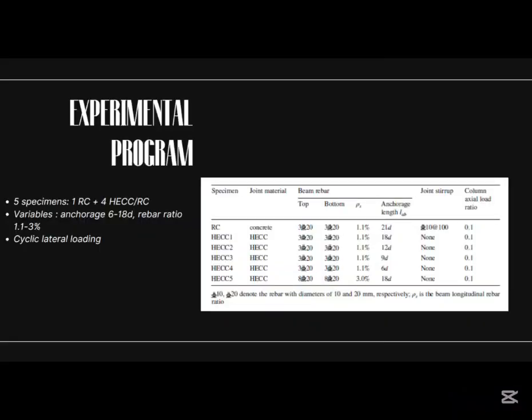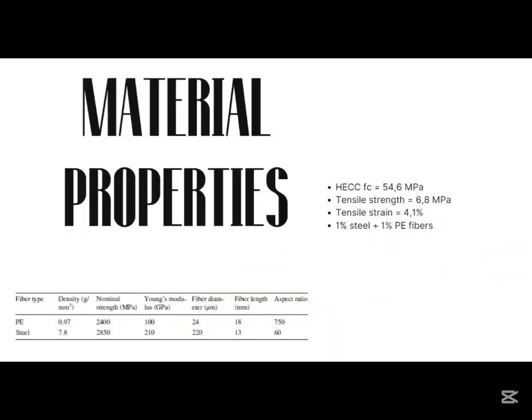The team tested 5 joints under cyclic lateral loading. One was a normal RC joint and 4 were HECC joints. The HECC used in the study had a compressive strength of about 55 megapascals, a tensile strength of 6.8, and tensile strain capacity of about 4%. It contained 1% steel fibers and 1% polyethylene fibers, giving it high toughness and excellent bonding.